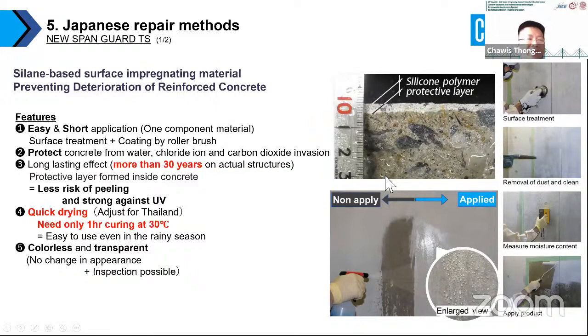Firstly, we want to show you the product for preventing deterioration of reinforced concrete. We call it the New Spanguard TS, where TS means Thai Silane, a silane based impregnation material. The silane based material forms a water repellent layer on the concrete surface, as shown here. It is used to prevent the intrusion of water and deteriorating factors. This water repellent layer is different from a waterproof coating, and it is possible to release the inside water, so it performs well.